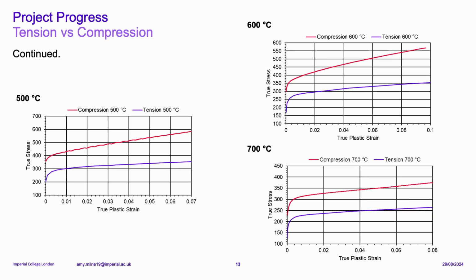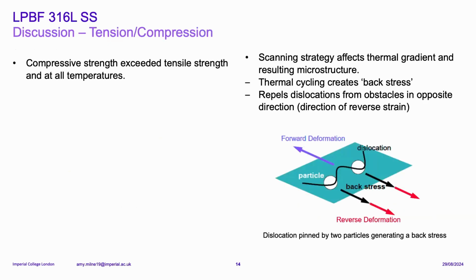So at 700 degrees, is it on here? It's had time to relax. There's more potential for hardening to occur. So the reason you've got the compressive strength exceeding the tensile strength for all temperatures is likely due to back stresses formed during the build process.